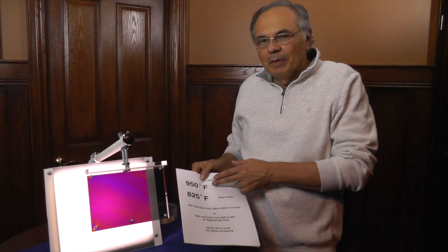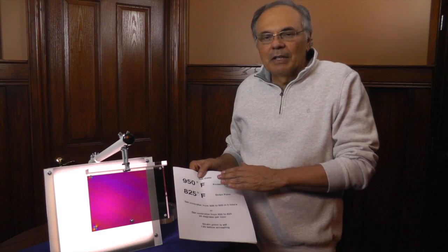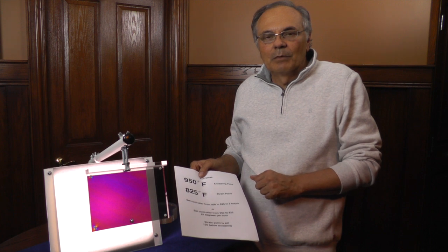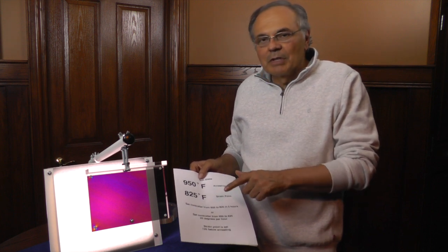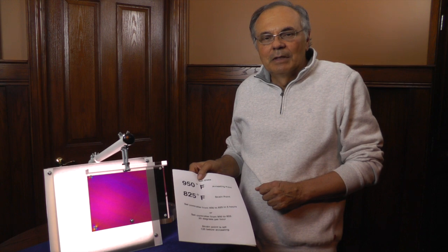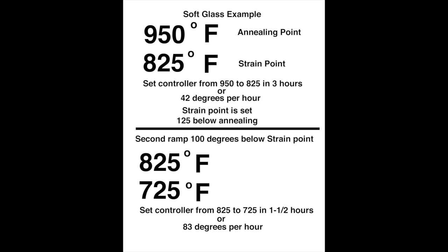So going from the annealing point to the strain point, I'm actually getting through that zone no matter where it is. So 125 degrees is going to be our rule of thumb. And then I'm going to show you some charts and show you how we can build an annealing profile. This chart is an example of annealing soft glass. I'm going to use 950 as kind of an average. It might not be the exact temperature you have for your glass, but this is a starting point. So 950 down to 825 is 125 degrees, and that's where you build your first ramp down.